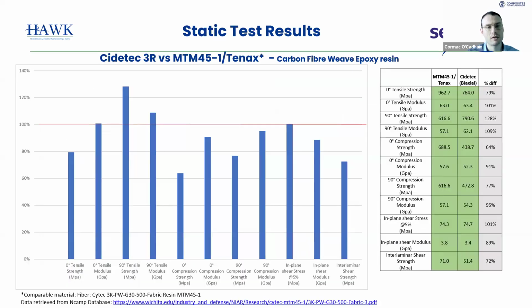So to look at this material, what we did then was we compared it with this baseline. So this MTM45. So this is one of the materials from the NCAMP database, and this line here is the values of that material, and we tried to compare this Cidetec 3R resin with those baselines. So we see here 0 degree tensile strength is about 80%. The modulus is quite similar. Our 90 degree is better actually, and our 0 degree compression strength is probably the lowest. So that's down there at 64%.